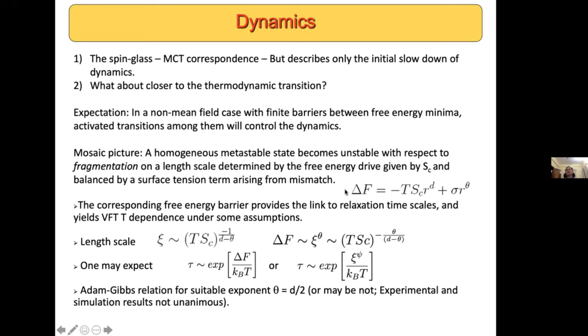And so in a form that's familiar from nucleation theory, one can write the free energy cost to forming a domain of a certain size as being given by a free energy lowering, where the lowering of the free energy is governed by the configurational entropy times the volume of the region, plus an increase in the free energy that arises from the surface tension. And this goes with a surface tension exponent, r to some power theta, and where sigma is now considered as a constant.